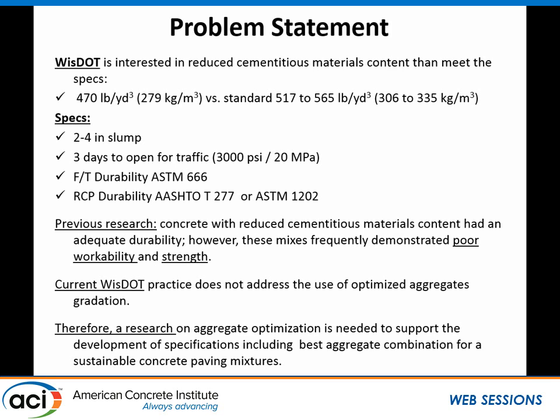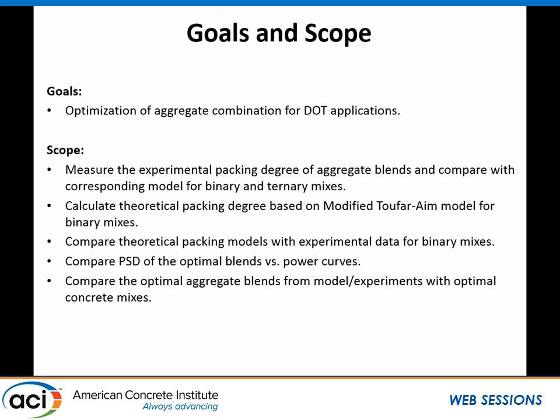We have to consider that if you want to use supplementary cementitious material with such a low cement content of 280, we have to work on aggregate packing to get the most strength. So therefore, we need to run aggregate optimization. This would be for concrete pavements, obviously, and like I said, we're going to talk about experimental, theoretical, and packing models, and then continuous power curves.